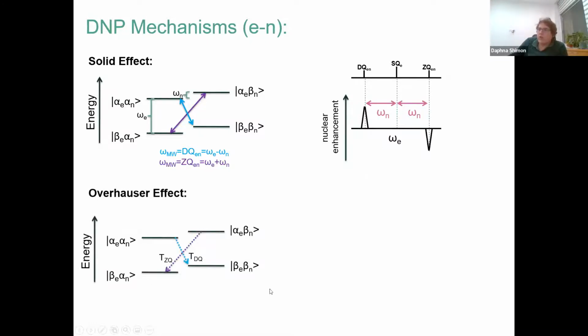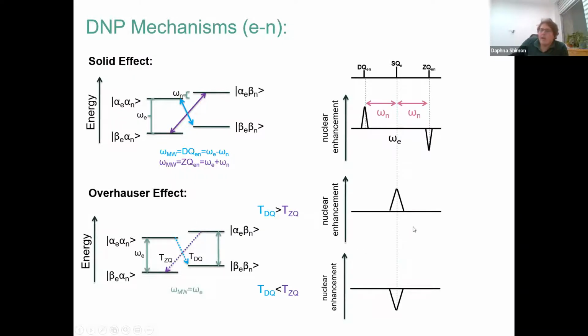For the Overhauser effect, we can look at the same spin system, but now if we have cross-relaxation between the electron and the nucleus, so double quantum cross-relaxation or zero quantum cross-relaxation, and if the cross-relaxations are not equal, then when we irradiate on the electron, what we get is enhancement. And so if the double quantum transition cross-relaxation is faster than the zero quantum cross-relaxation, you get negative enhancement. And if the zero quantum cross-relaxation is faster than the double quantum cross-relaxation, you get positive enhancement. And so it's really just a play between the different cross-relaxations, and whichever one wins determines the sign.